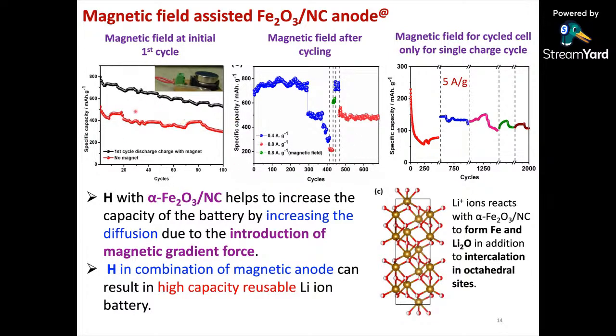You can easily see the enhancement in the capacities is mainly because of the diffusion of the lithium ion due to the introduction of these magnetic gradient forces. Now this is the number of cycles. We have done almost up to 2000 cycles, and let us start here. Very close to 200 to 300 cycles, with a current density of 0.4 ampere per gram, you can see that the performance started degrading without any magnetic field. Without any magnetic field, we increased the current density to 0.8 ampere per gram, and still the capacity decreased to almost 200 milliampere hour per gram.